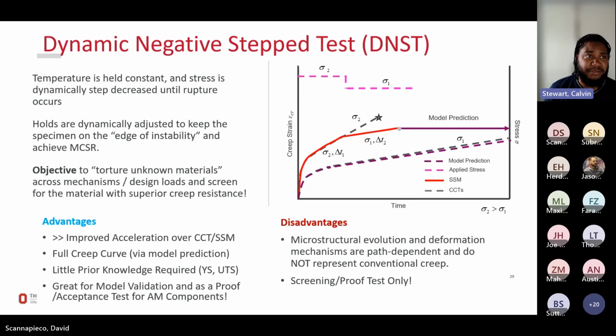For that, we developed the dynamic negative step test, where instead of stepping up the load and having these very fixed hold periods, we dynamically step down the load and we closely track and dynamically adjust these hold periods to keep the material on the edge of instability. Basically, we create a test that tortures the material until it fails.